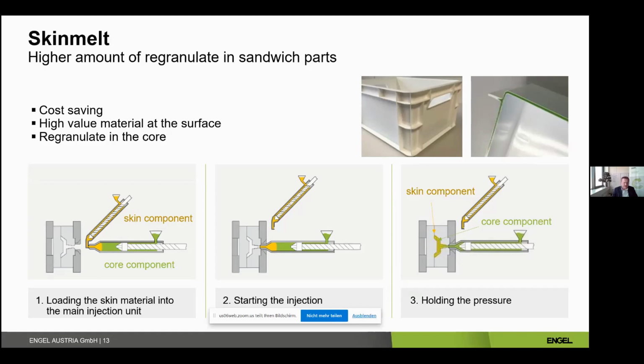You have two of them, one for the skin melt and one for the core component, which means loading the main injection unit with the skin component from the front side, and with the core component from the rear side, and then inject it together into the mold, and then the skin is laying on the wall of the mold, and then the core component is pressed into the center of this.